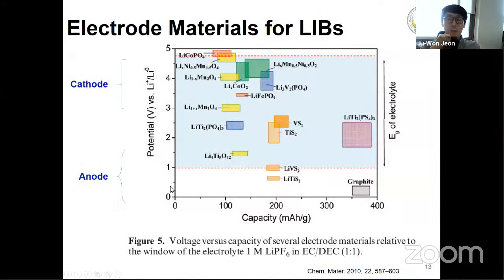Okay, these are some of the candidate electrode materials for the lithium-ion battery. The x-axis is the capacity and the y-axis is the potential versus lithium. If it has a high potential, around 4 volts, higher than 3 volts, it can be used as a cathode material. And if the redox potential is low, less than 1 volt or less than 2 volts, it can be used as an anode material. So for example, if you use lithium cobalt oxide as a cathode and graphite as an anode, you can obtain a cell voltage around 3.8 volts or around 4 volts.